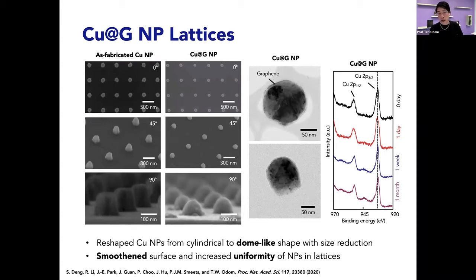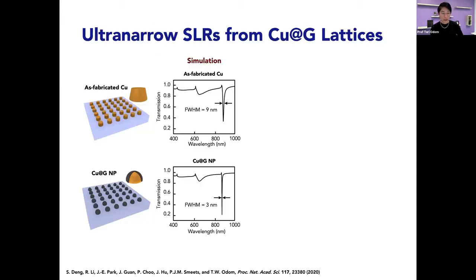We used XPS to test whether the particles would oxidize. And you can see these dominant copper peaks, and they look good. The copper oxide peaks would form right around here, 945, and a little bit here at lower binding energies. So there might be a little bit if you squint hard enough, but for the most part, the graphene does a really nice job of covering the surface.